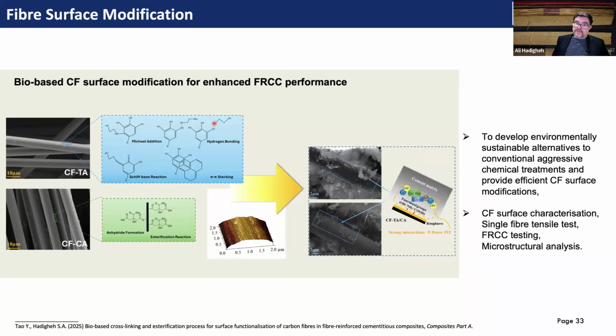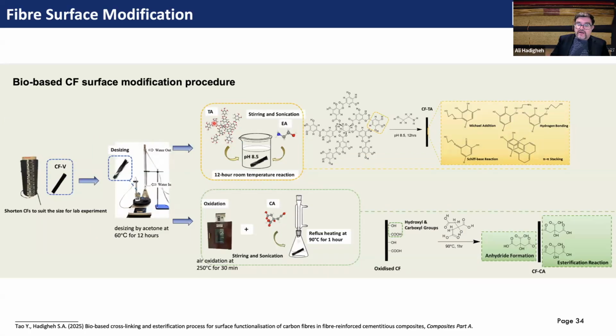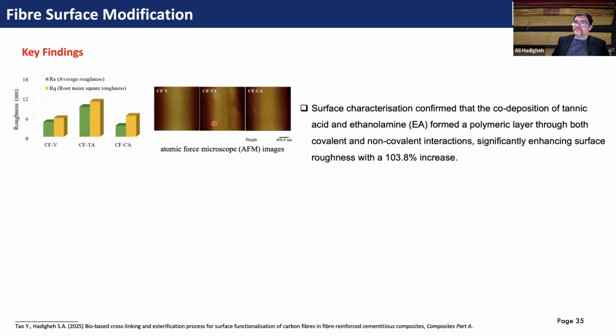With my PhD student, we looked at bio-based carbon fiber surface modification. And why did we select that? Because the construction industry is usually a conservative industry and doesn't want to deal with very harsh chemicals and materials. So with these bio-based materials, which were tannic acid and citric acid, very weak acids, we functionalized the surface of our carbon fiber and improved the performance. We basically desized our carbon fiber first, and then we exposed them to tannic acid or oxidation and citric acid, and then we functionalized the surface with hydroxyl groups, and then we tried to incorporate them into cementitious material.